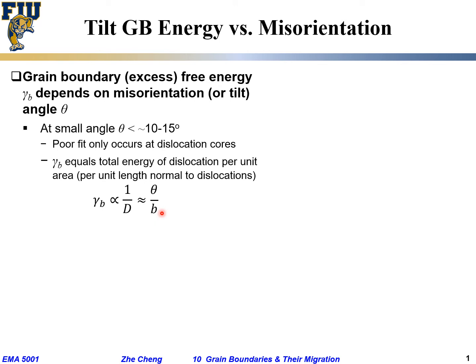Based on this relationship, we have the conclusion that the grain boundary energy for this low angle tilt boundary is proportional to theta, the tilt angle between neighboring grains.